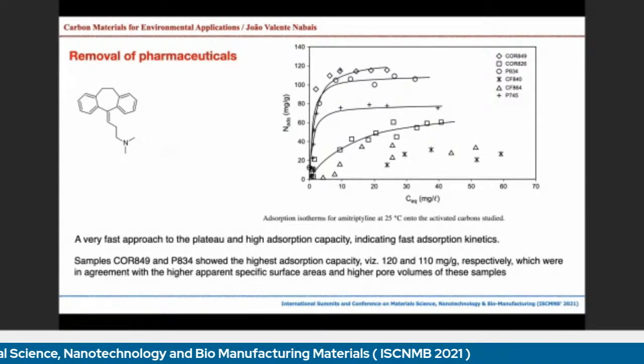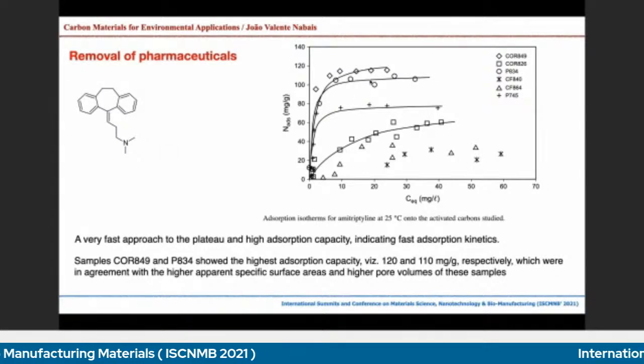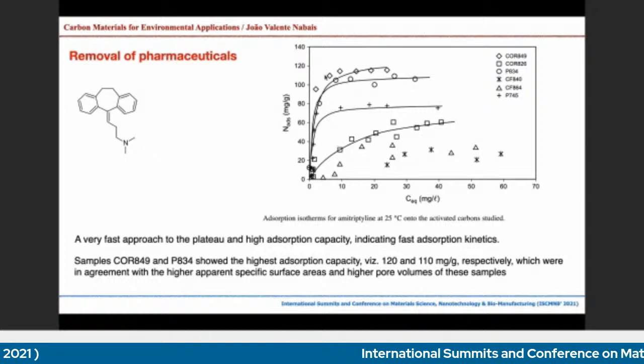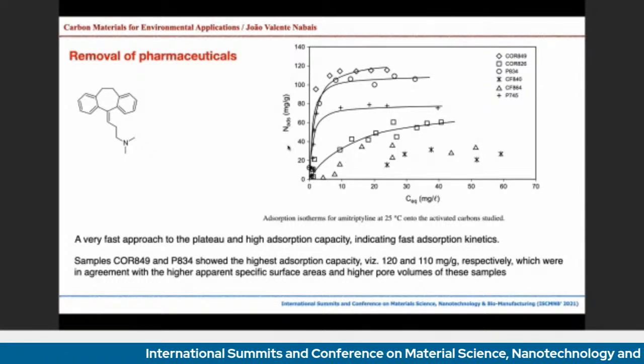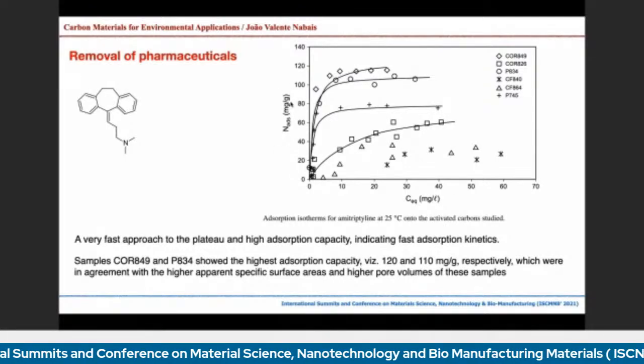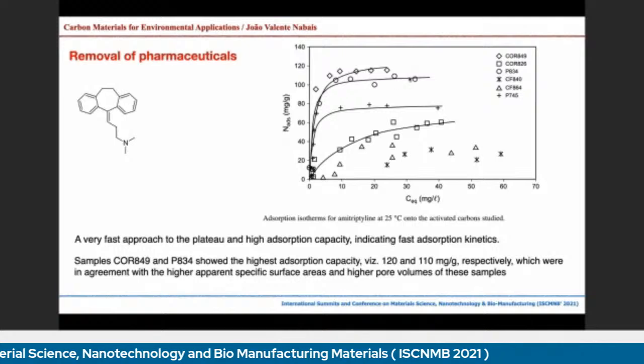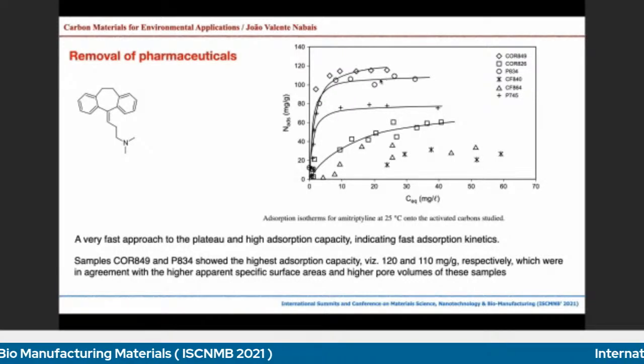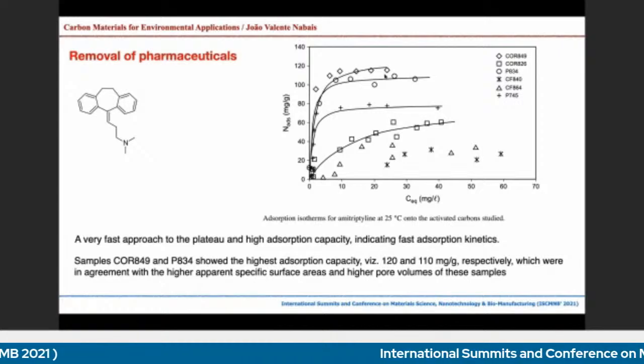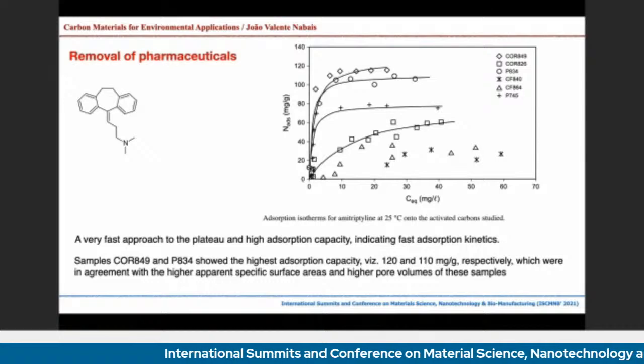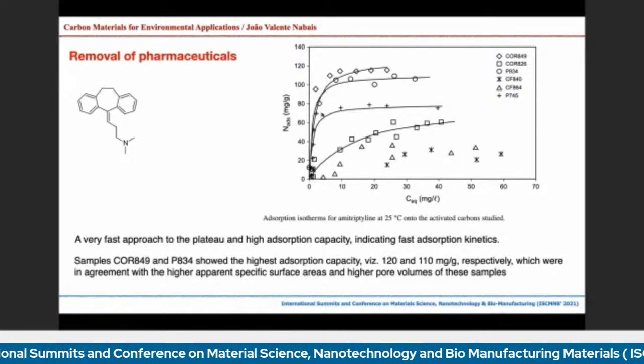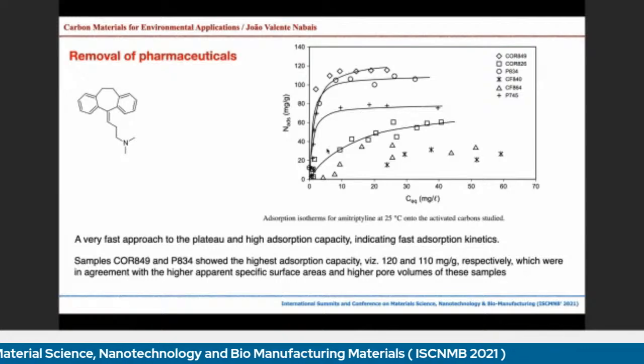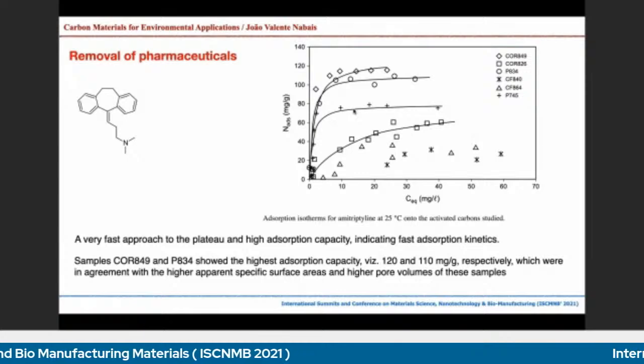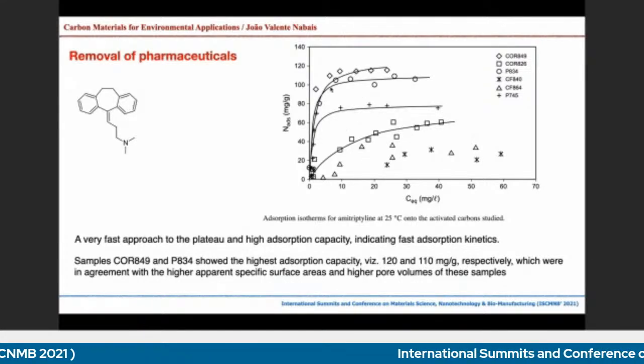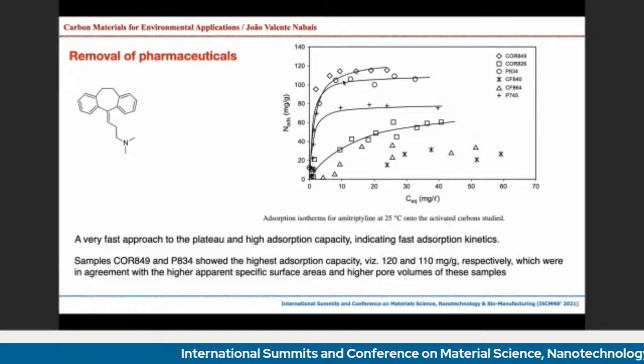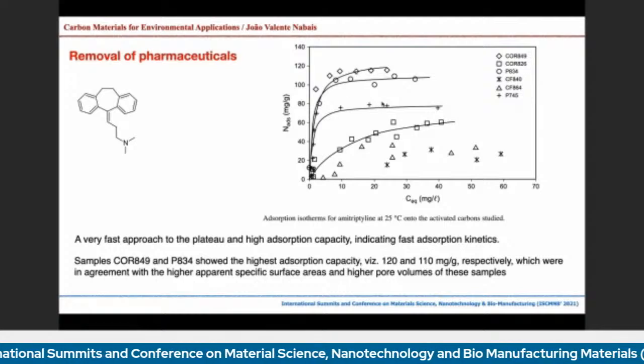This is what our experimental output looks like. So we produce these isotherms of absorption. You can see here the amount of absorption in milligrams per gram of carbon. And you can see here that there is a plateau most of the time, meaning that from here you can take out the maximum absorption capacity of the materials. This very, very fast approach to the plateau means that the absorption is very fast. It has a high kinetic property. And also you can see here that the amount absorbed is very much related with the surface characteristics, porous characteristics of the materials as well,